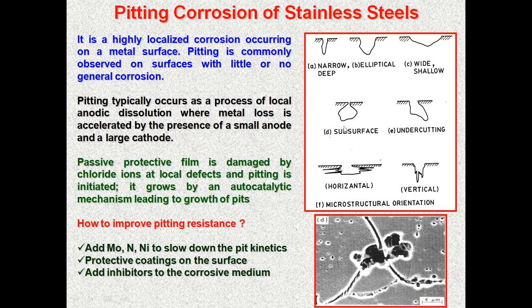And when it goes beyond the required depth, then it gives the site for corrosion cracks to start due to fatigue or mechanical fracture. This typically occurs when there is an anodic dissolution selectively due to the halide ions, as I told you. Since it is a small anode and there is a large cathode, it is also accelerated in nature, and there is an autocatalytic mechanism: once chloride enters this pit site and the pit is growing, it continues to grow, and you will never be able to stop it, because the chloride that is getting collected in this pit will always give the possibility for the pit to grow.